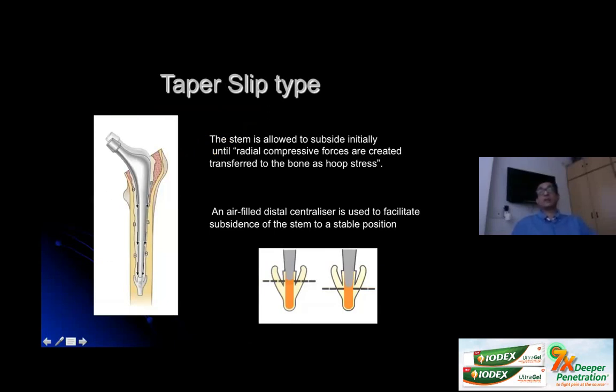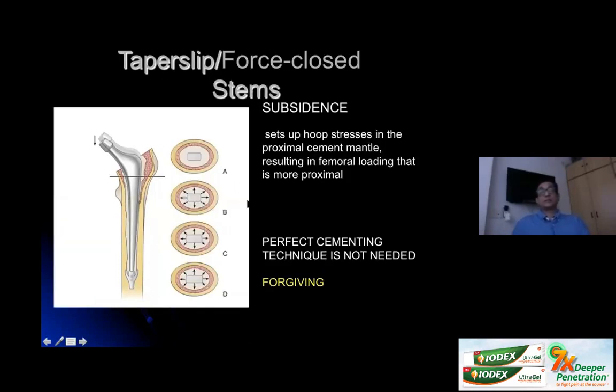So basically what happens in the taper slip stem is that gradually the stem subsides by a few millimeters initially, which leads to radial compressive forces which are transferred onto the proximal bone, and which passes the normal stresses onto the bone and prevents stress shielding of the bone. The most important part of this stem is the centralizer, which usually has a small air-filled gap for the stem to subside and subsequently become stable gradually. As the stem subsides by a few millimeters over the first year or so, there are hoop stresses generated in the proximal femur, which prevents stress shielding of the bone.